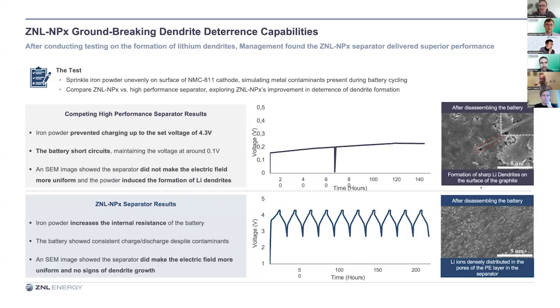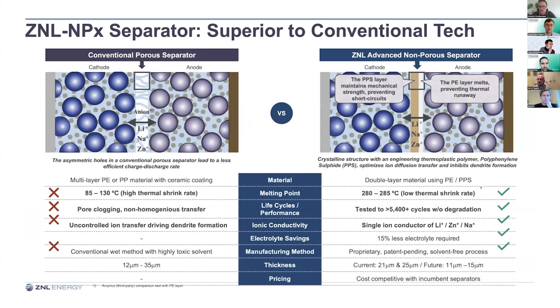Basically what happened is, if you look at this slide, when you get a thermal event, for instance dendrite formation, the PE or the PP melts down and shuts off the ions. So we see on test that we go up to 80 degrees, where the glass transition or the melting point of the PE is, and it stops the ions. So it goes up to 80 and then it just drops. So you don't get the uncontrollable thermal events.